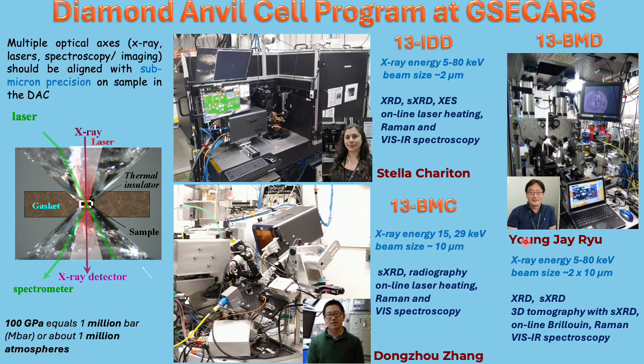At 13 BMC station, we have fixed energy at 29 keV and beam size around 10 micron. And most important, we are using a 6-axis diffractometer that allows us to study full reciprocal space of the sample and be able to rotate the sample and detector to different positions. And Dongzhou Zhang is responsible for this station. And of course, if you have any questions about where to run your experiment, you contact me.